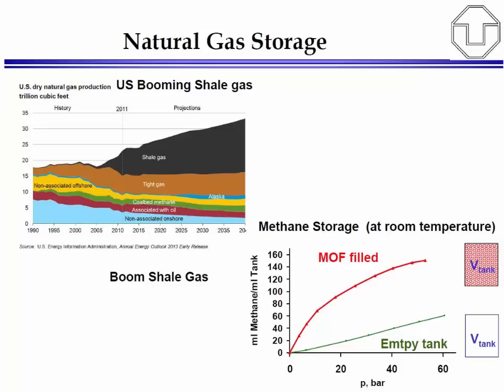And this is a topic that has recently been quite interesting, especially in the US, where the shale gas has boomed. Now, I made this slide, I think, several months ago. Now we see already that the shale gas has some problems because oil has become very cheap. But we will see what the future will bring. But the message is that in an intermediate pressure regime, especially at about 50 bar, a MOF can be quite useful to enhance the storage capacity of a tank system.